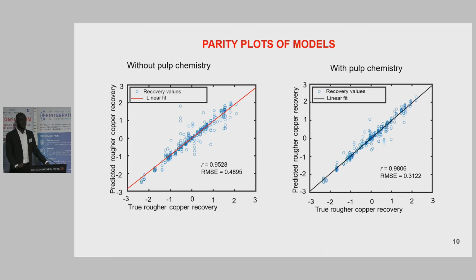So going through literature, we realized that even though machine learning models have higher accuracy and very good predictive performance, the work that has been done so far mostly doesn't include pulp chemistry parameters. So what we did with the little data that we have on pulp chemistry from BHP is that, first of all, we modeled with just plant variables, and that is the image on the left. After that, we included the pulp chemistry variables in terms of pH, Eh, dissolved oxygen, and temperature. And from this slide, we can see an improvement in the performance of the model that we developed.